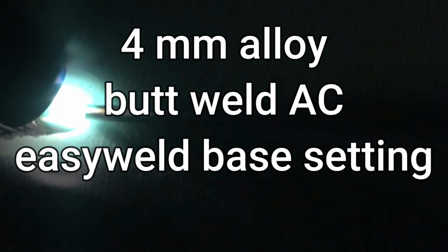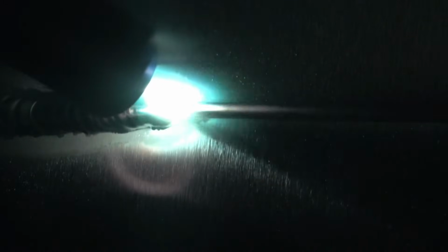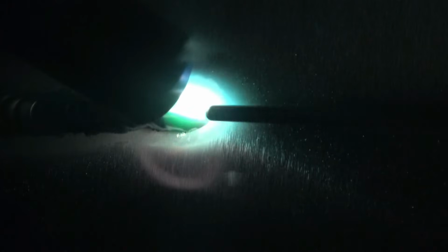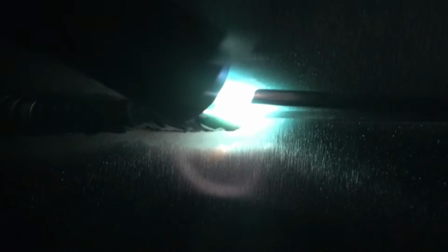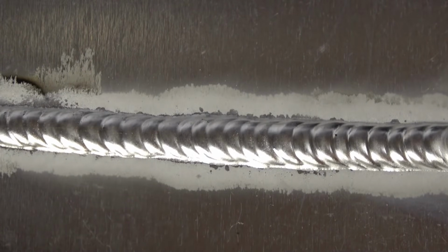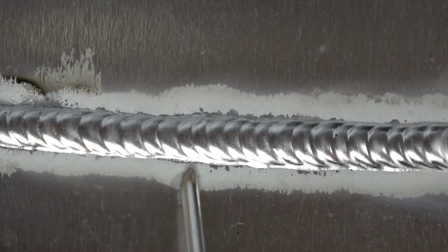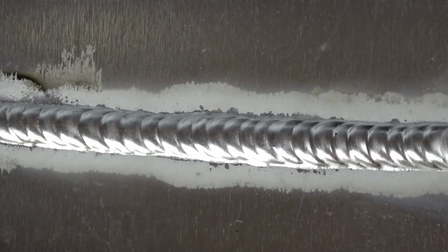This is a butt weld in 4mm alloy using the easy weld base settings. It's running in nice and smooth, very stable, constant arc. It's going exactly where I point it. For a straight out of the box weld, that's pretty good. You can clearly see where the AC's cleaned the material either side of the weld. I'm very happy with that, very happy indeed.